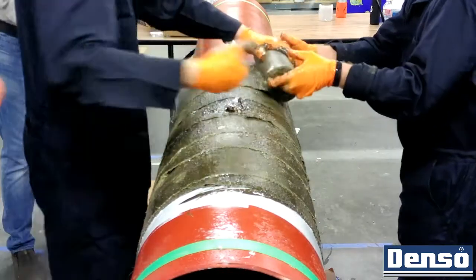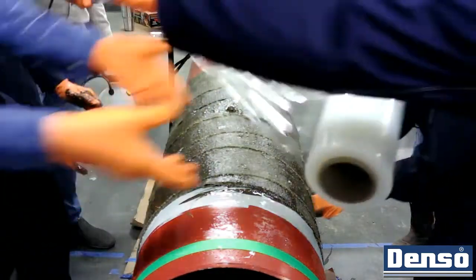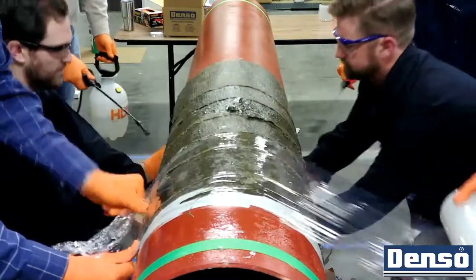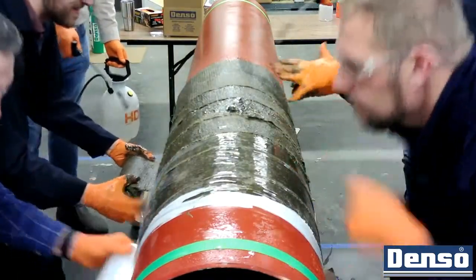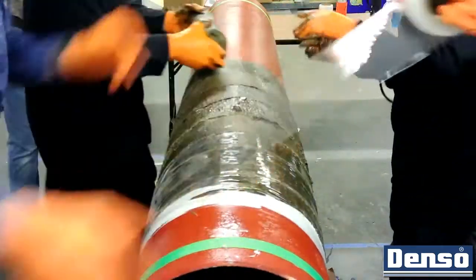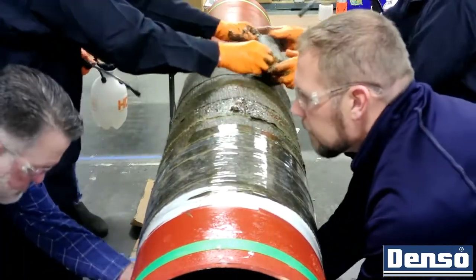To ensure the ends lay flat and the resin can be retained, overlap the starting and trailing edge of the previous roll by a few inches on each side. 2 to 3 passes with the Denso Polywrap should suffice.